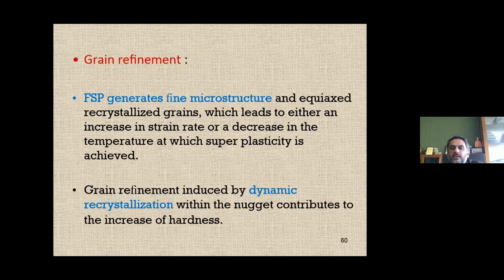Another reason is the grain refinement, because precipitates are also deforming and reducing their size, and the matrix, right? Whatever the matrix you have, that also refines during the process because you are doing friction stir processing. So FSP generates fine microstructures and equiaxed grains, right? Which leads to either an increase in strain rate or a decrease in the temperature at which the superplasticity is achieved. So you are doing a superplasticity test.